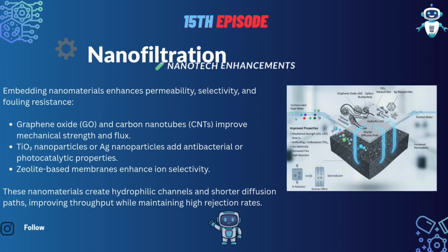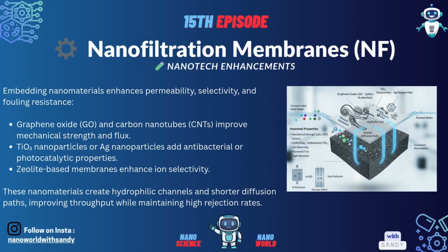Nanotech enhancement. This is where nanoscience elevates the technology. By embedding nanomaterials, we solve the two biggest issues: permeability and fouling. Materials like graphene oxide and carbon nanotubes are added to the polymer layer. They create highly hydrophilic channels and shorter diffusion paths, which dramatically increase water flow, or flux, without sacrificing purity. Even better, embedding TiO2 or Ag nanoparticles can give the membrane antibacterial or photocatalytic properties for self-cleaning.